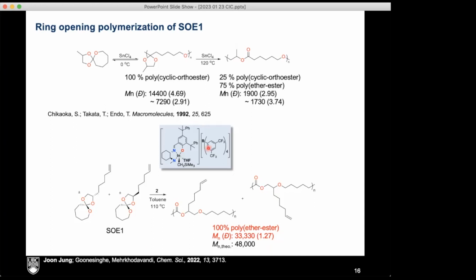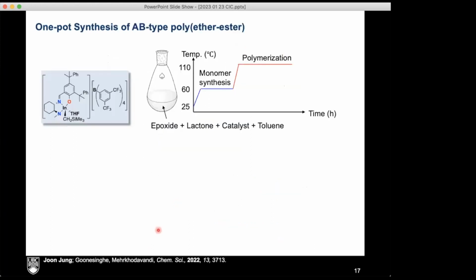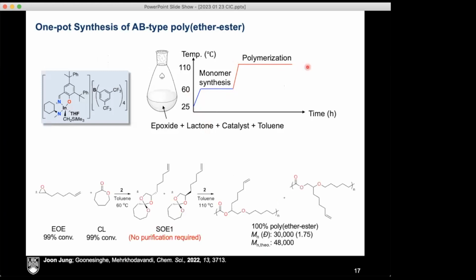So the fact that we can make the monomers and polymerize them with the same catalyst under different conditions made June go, huh, okay, so why don't we just do everything in one pot? And this is what he did. He did the monomer synthesis at a certain temperature, jacked up the temperature and polymerized it at a higher temperature.